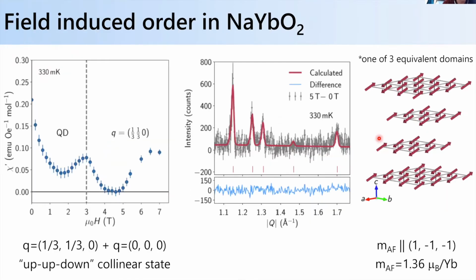And so where it gets interesting on this particular material, because other than just seeing nothing, you often want to have something to ascribe to a model, and that usually requires seeing something. What we can do is look at the susceptibility as a function of field at low temperature. So this is 330 millikelvin. As you sweep field, the susceptibility drops. And then eventually you have a peak in the susceptibility, as you, we will argue, cross a phase boundary. Then you enter what looks to be an ordered state where the susceptibility bottoms out, and then it starts coming back up, okay?